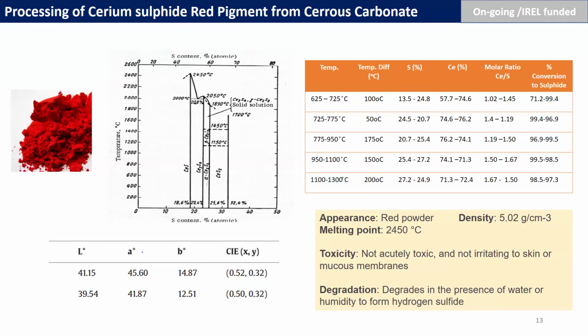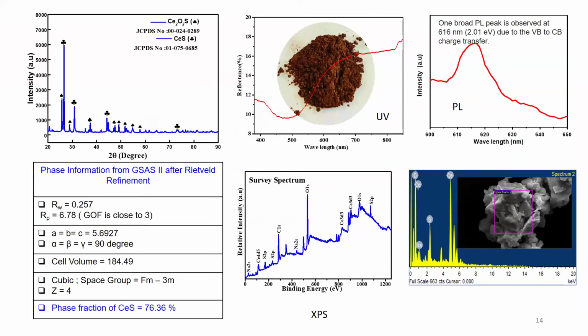You can see here that it can form the red color only in this narrow window, alpha cerium sulfide. Very difficult. So we started addressing this issue, and we have made many experiments, with and without urea, with and without thiourea, and all we have checked. Because the cerium carbonate is supplied by IREL, and sulfur is procured from the local market to make this cerium sulfide, you can produce cerium sulfide, but you cannot easily produce a red cerium sulfide, which is extremely difficult and requires hydrogen purging, and also very careful monitoring of the gas pressure. We have done it, and I'm telling you.